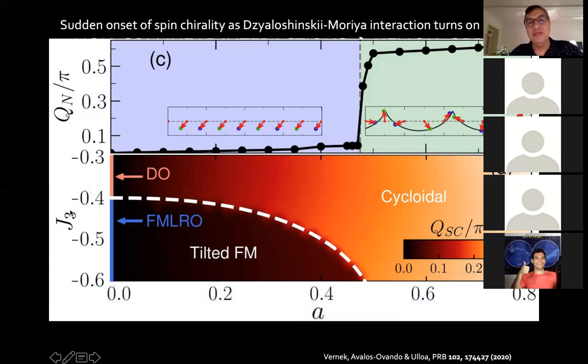On the other hand, if this other parameter, which is the J, remember, of the third neighbors, is larger, more or less negative, then there is a gradual progression of that cycloidal number instead of a sudden phase transition. So if you're interested in studying magnetic systems, this tells you that putting magnetic systems in these interfaces will give you a very rich phase diagram.